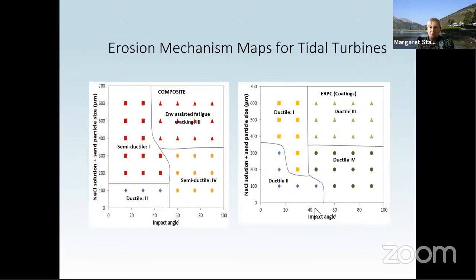What we developed as a result of our research was two series of maps, one for the composite and one for the coating. So we found that our coating performed in a ductile erosion mode, but there were differences in the regimes. But for our composite, we got environmentally assisted fatigue cracking on the surface at the higher impact angles. So basically, what we saw in this regime here is that the presence of the chlorides, even in a polymer-based composite, has actually caused an accelerated cracking regime.